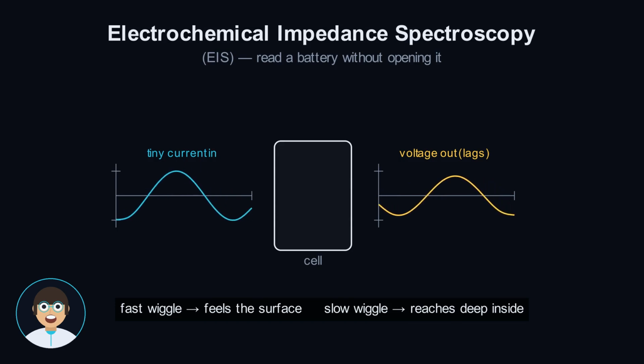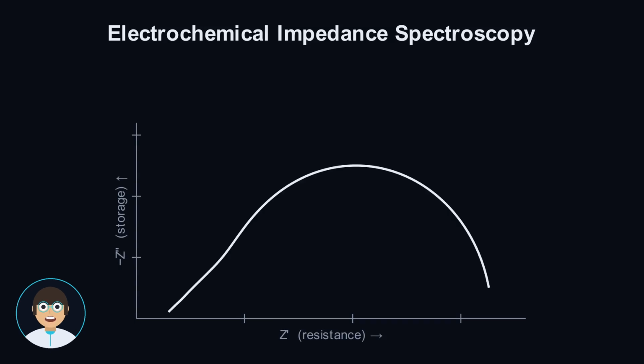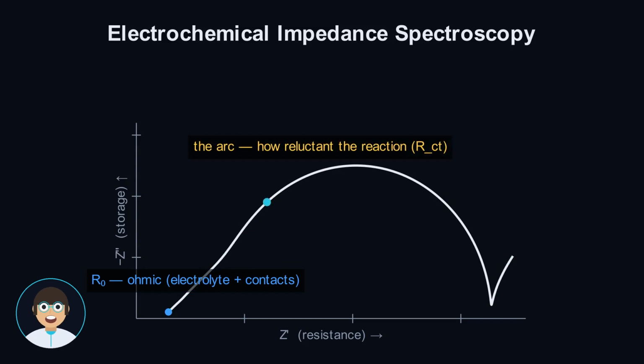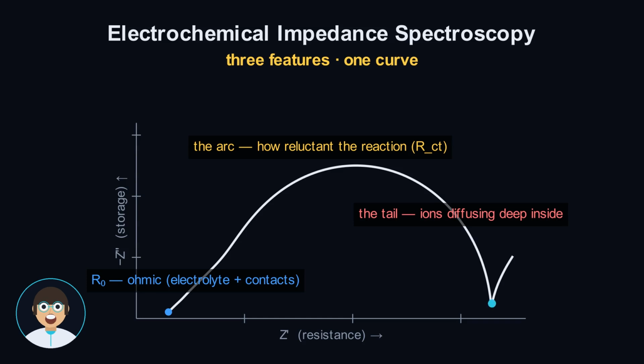Plot the answer the right way and you get this shape, the Nyquist plot. Plain resistance runs across the bottom. The springy storing part runs up the side, and you read it left to right like a sentence. The left foot is the ohmic resistance, mostly the electrolyte and the contacts. We call it R0. The arc in the middle is how reluctantly the chemistry reacts, the charge transfer. And the long tail at the end is ions slowly crawling deep inside, diffusion. 3 features, 1 curve. Hold that picture.